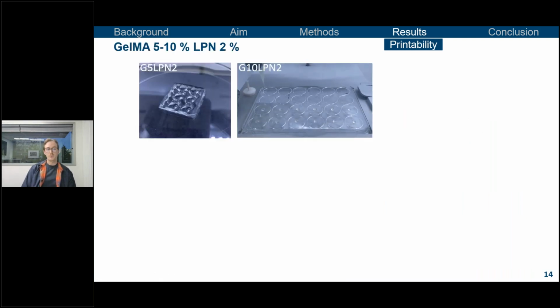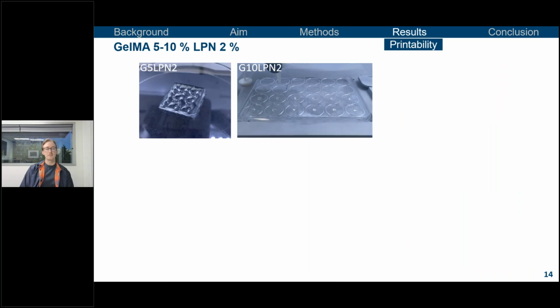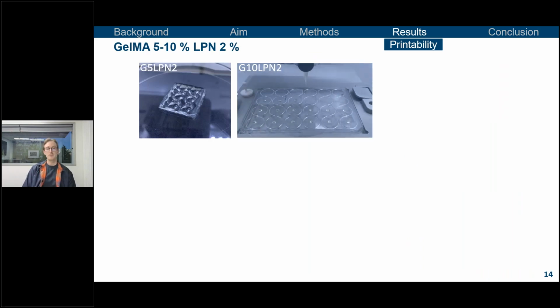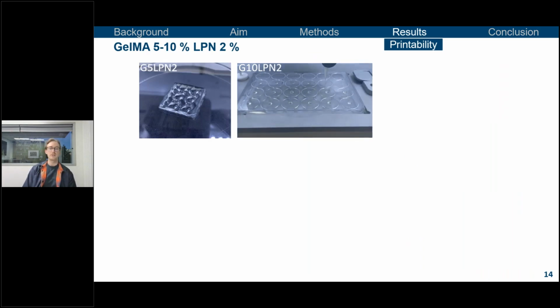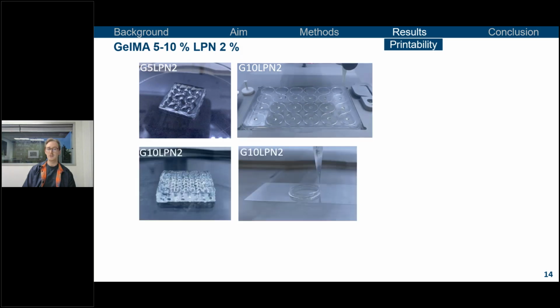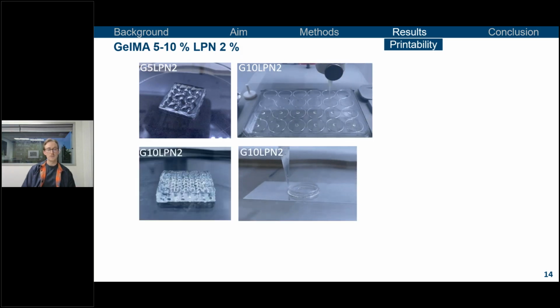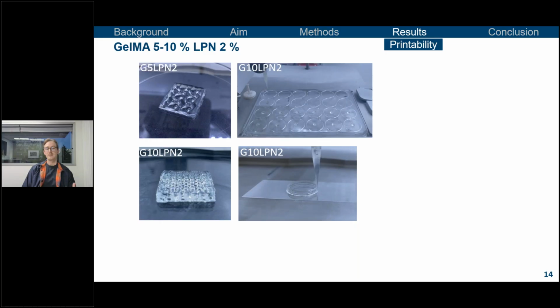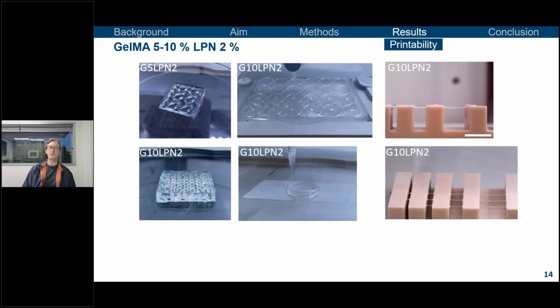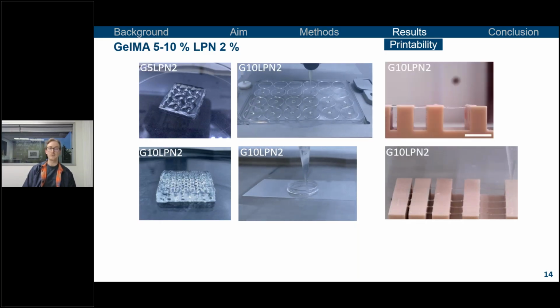We're able to show also, with printing GelMA 5 to 10% with laponite 2%, we can create a number of different structures and geometries, ranging from different lattice structures to droplets, to taller lattice constructs, to cylindrical constructs, or even single fiber constructs using these bridging techniques. So we're able to show that it is capable of printing this range of geometries and sizes of up to approximately 10 millimeters, showing that it's capable of being used for extrusion-based printing.